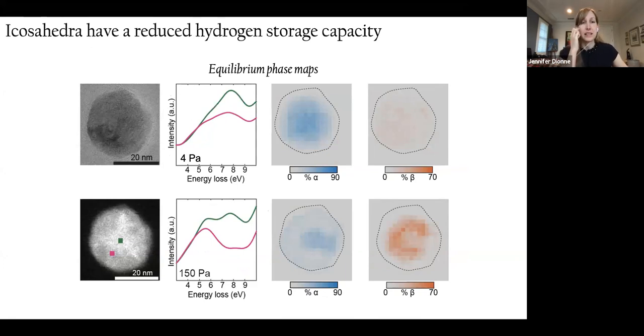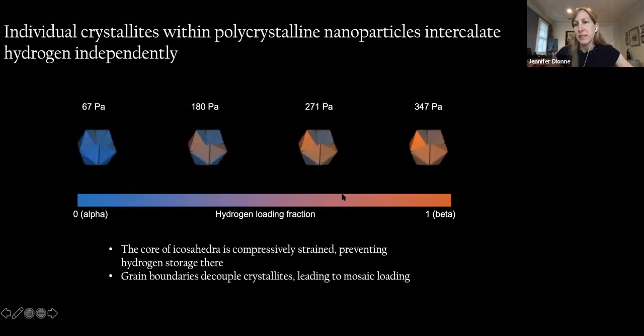So the icosahedra are actually compressively strained. So there's more strain at the core of the particle than there is at the surface. And that strain makes it much harder for the hydrogen to intercalate into the core of the icosahedra. So at intermediate hydrogen pressures, we find that the core is unhydrogenated, and it's really only the outermost shell that is hydrogenated.